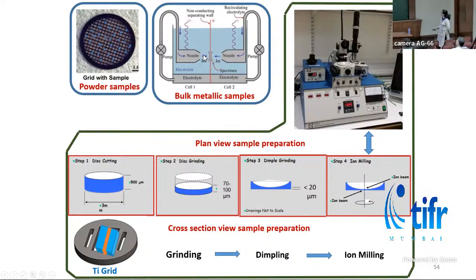There is an electrolyte bath, so a suitable electrolyte is selected, and there are fine nozzles. The sample is first thinned down to 100 micron, and it is mounted vertically in this bath, and electrolyte is sprayed by these nozzles, which makes the sample electron transparent. Other samples can be made by using these steps.